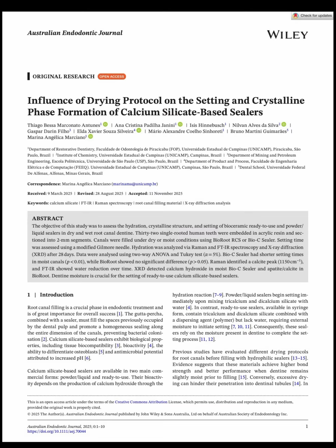Raman spectroscopy identified a calcite peak in both sealers, which is associated with the carbonation of the material during setting. For the X-ray diffraction phase formation, after 28 days, calcium hydroxide was detected only in the moist BioC sealer group, and BioRoot showed evidence of apatite and calcite but no calcium hydroxide peaks in this specific model.